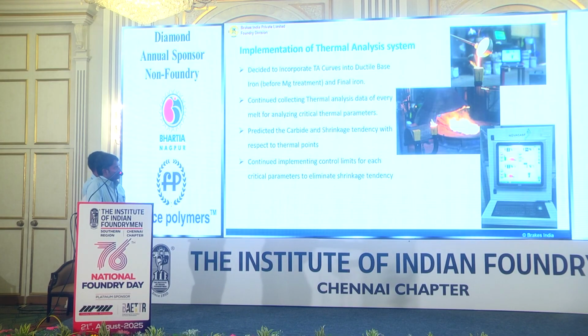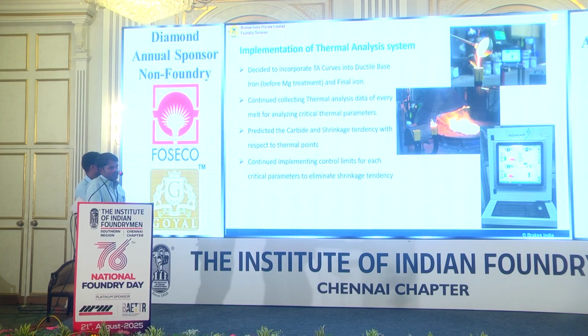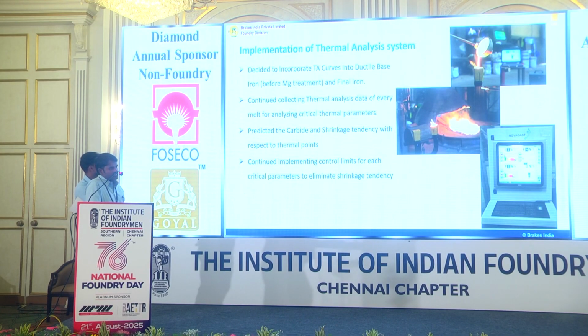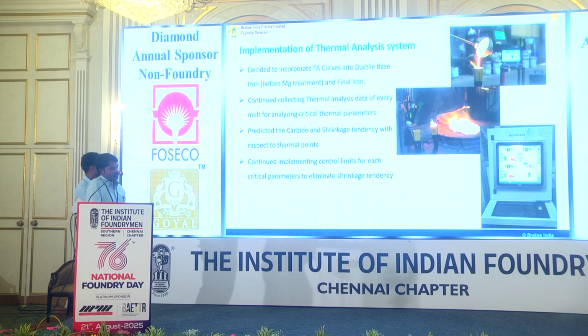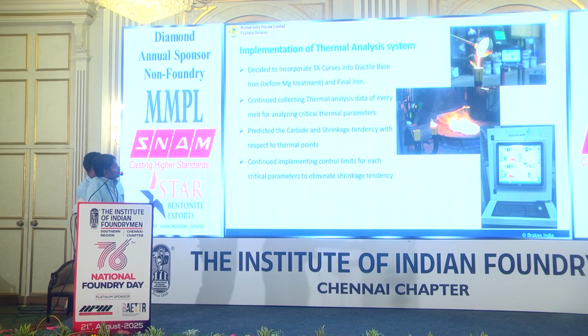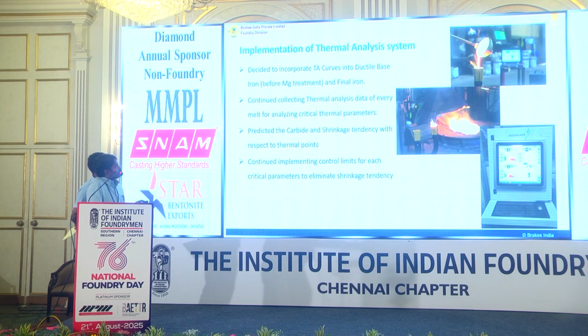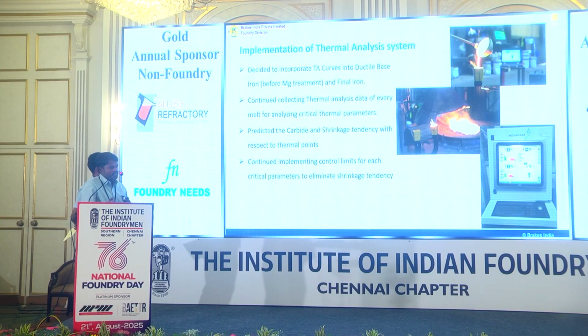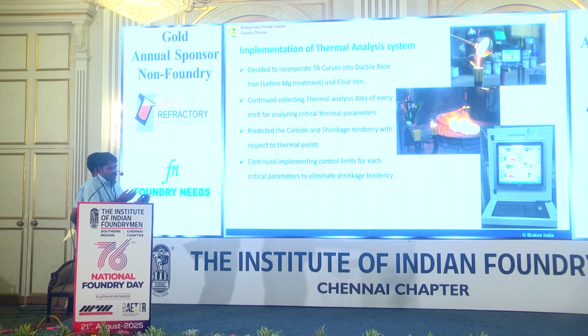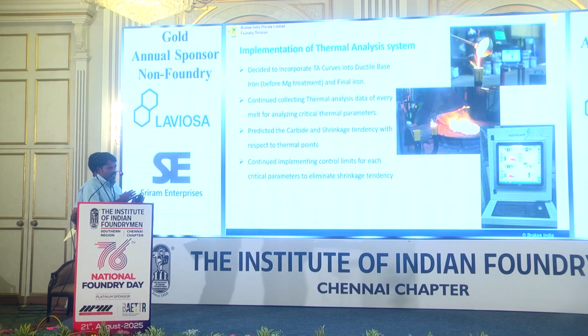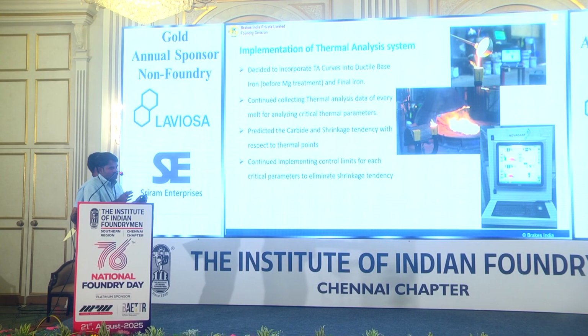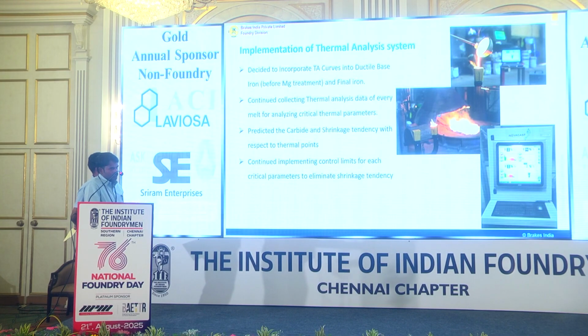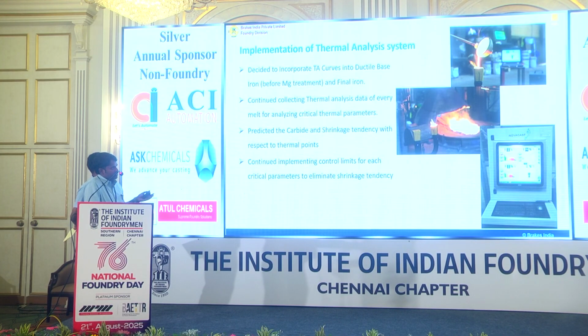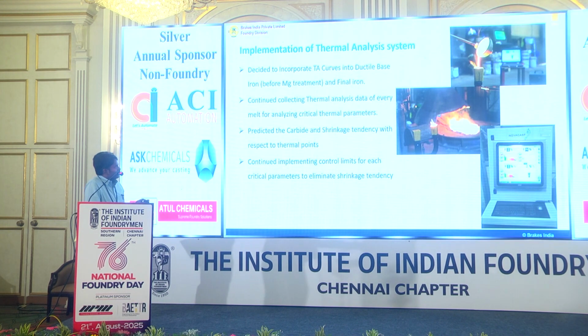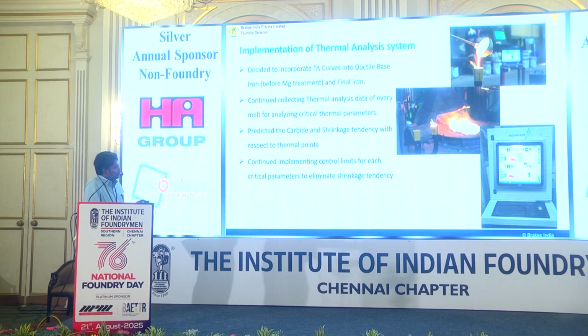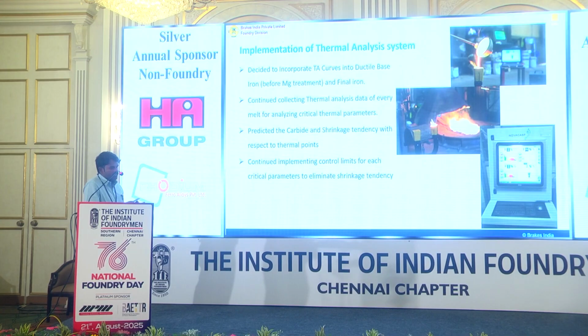So in one of our lines in the Brakes India unit, we implemented all those thermal analysis parameters stage by stage, and we achieved shrinkage defect reductions in one of our lines. How we achieved this, we can describe here. We decided to incorporate all the thermal analysis curves in the base metal as well as in the final metal. By continuously collecting all the data over the year, we analyzed it based on the good, bad, and actual casting defects. We defined the specifications for all the parameters like carbon equivalent, carbon at TL, as well as TL, TE low, everything. We predicted the carbide and shrinkage tendency with respect to thermal points, and continued implementing control limits for each critical parameter to eliminate shrinkage tendency for each part number.